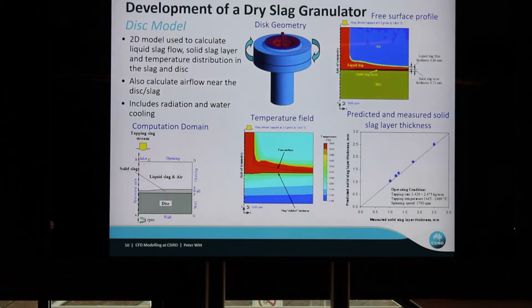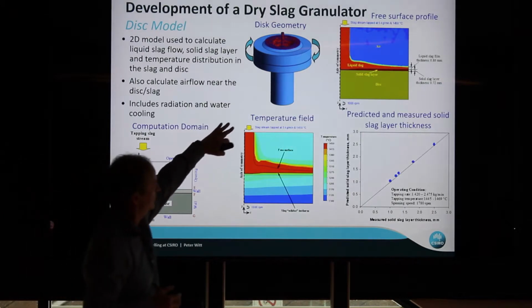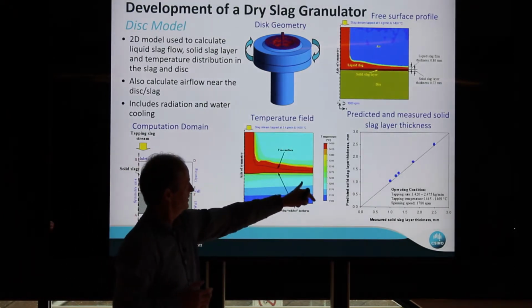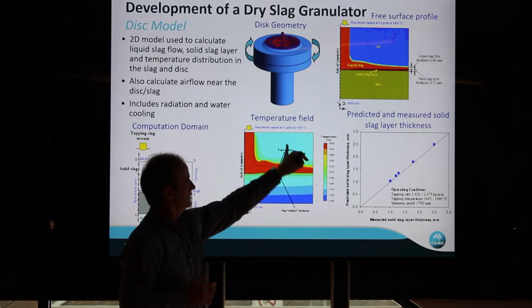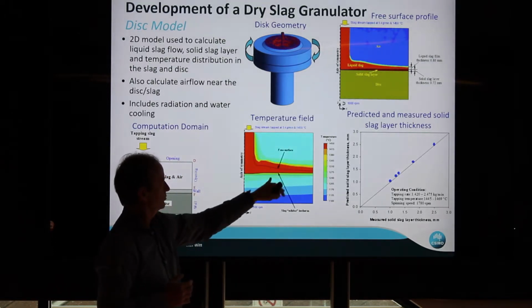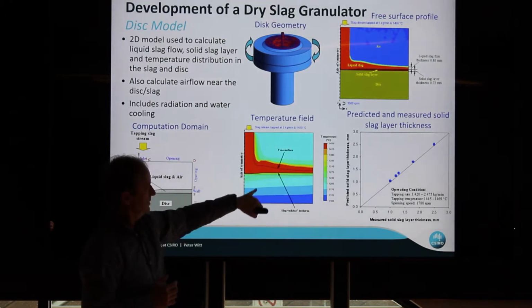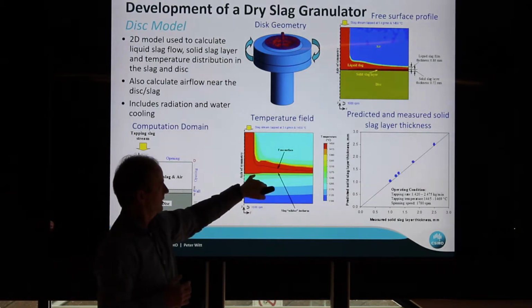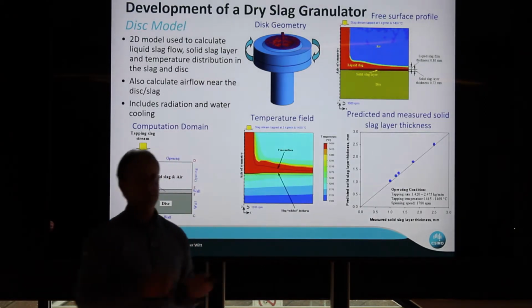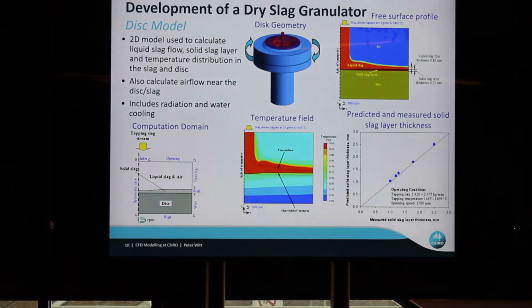So the disc model, we used a 2D model where we basically have the slag coming in onto a solid disc. The slag spins out. We can then look at the flow, the temperature profile, look at the conjugate heat transfer through the disc, and then predict a solid layer, because the idea for something like this in a lot of metallurgical processes is if you freeze the material you're producing onto, whether it's the refractory or onto the disc, you then provide an insulating layer that prevents the disc being melted away or eroded away.